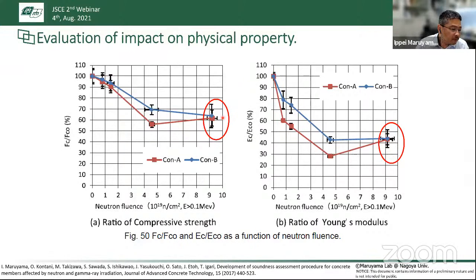In the case of the highest neutron fluence, we have some trouble. I will not go into detail, but due to some capsule restraint condition, there was some increase of the concrete specimen. So that is why we see some anomalous behavior at the last neutron fluence case.